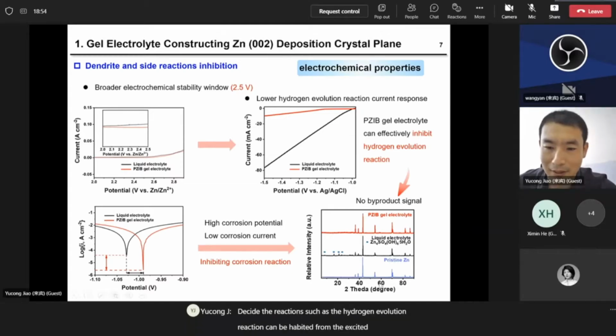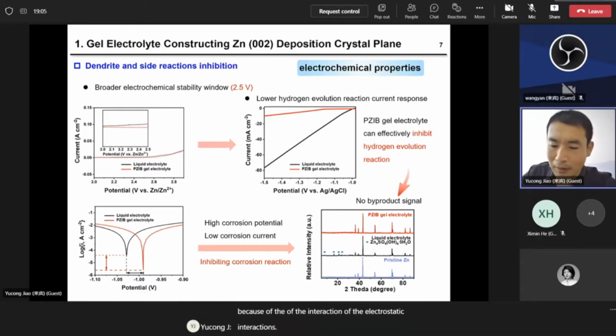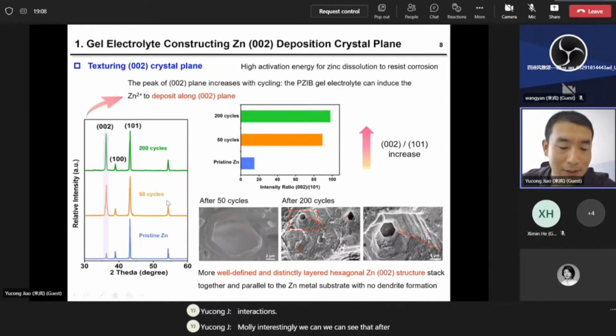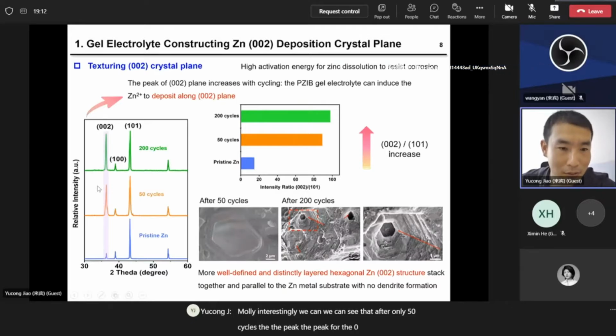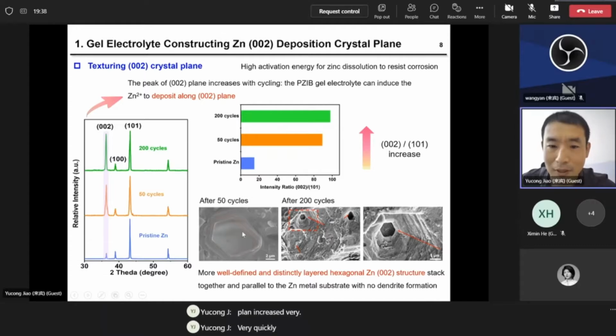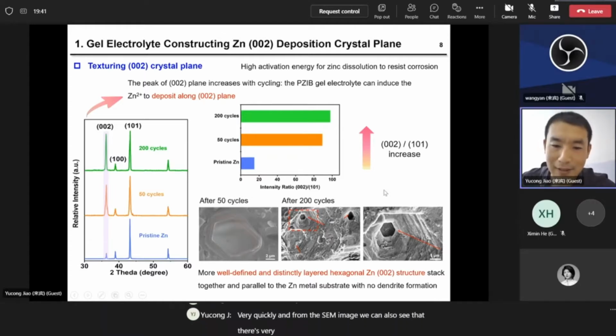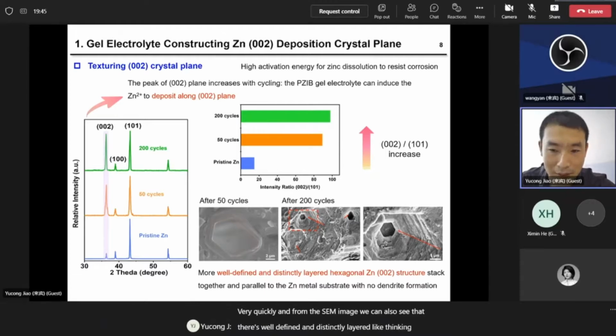From the XRD result, we can see that there's no byproduct with the zwitterionic gel electrolyte because of the electrostatic interactions. More interestingly, we can see that after only 50 cycles, the peak for the 002 crystal plane increased significantly. The 002 plane has a much higher activation energy for zinc dissolution, resists the corrosion, and helps to inhibit the side reactions. With the help of the ionics, we can find that the 002 plane increased very quickly. And from the SEM image, we can also see a well-defined and distinctly layered hexagonal zinc structure.